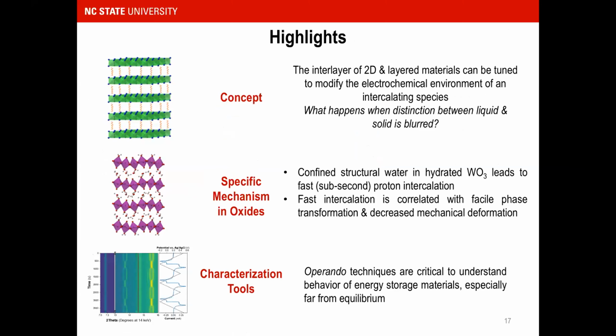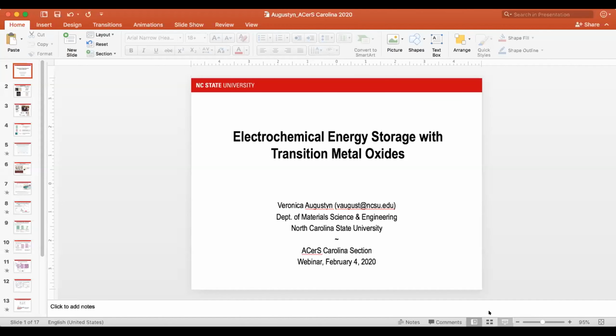So to summarize, I wanted to share with you this concept of how we can tune the interlayer of materials and how that can affect electrochemical behavior, in this case, energy storage processes. A particular mechanism that we've discovered in these tungsten oxides, where the presence of the structural water is really about minimizing kinetics and enabling very quick phase transformations to take place. And then the importance of studying these materials using operando techniques. In this case, we had both the AFM as well as the X-ray diffraction to bring us the full story. And with that, I'm happy to take any questions you may have.